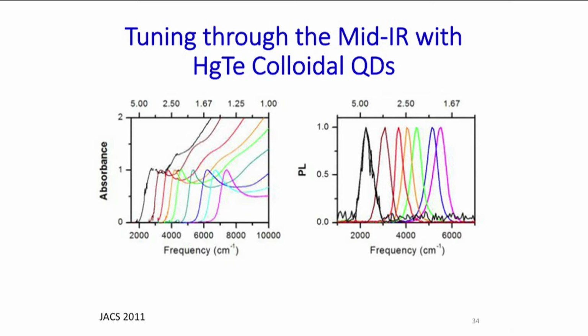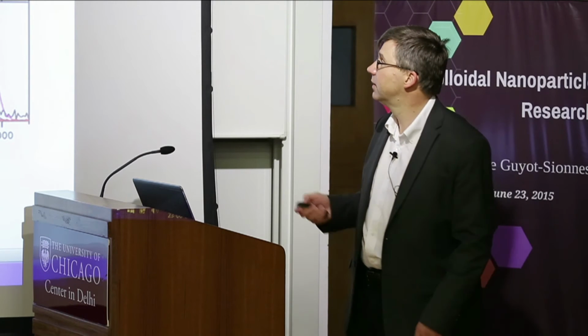This shows how the absorption tunes with size. These are particle batches of about 3 nanometers in size and about 12 nanometers in size, smoothly tuning as the particle size gets bigger. The energy, this is in wave numbers, gets smaller. And then those particles also fluoresce. And here we show the typical plots where all the fluorescence is normalized to 1 to make a pretty plot.